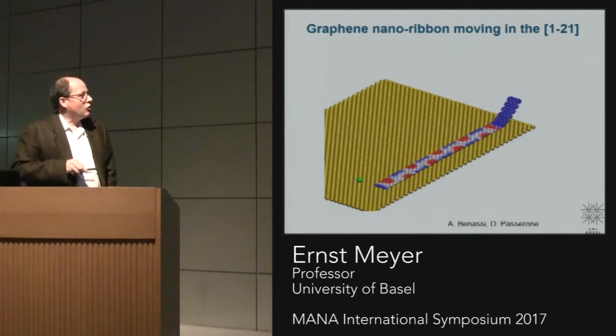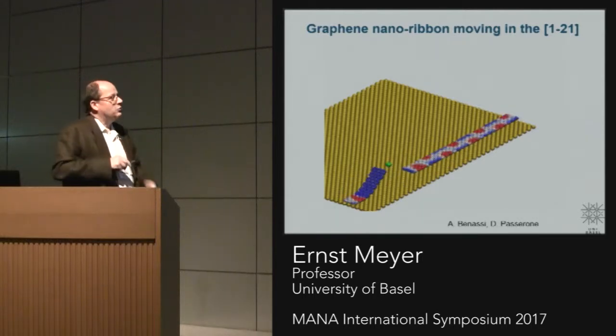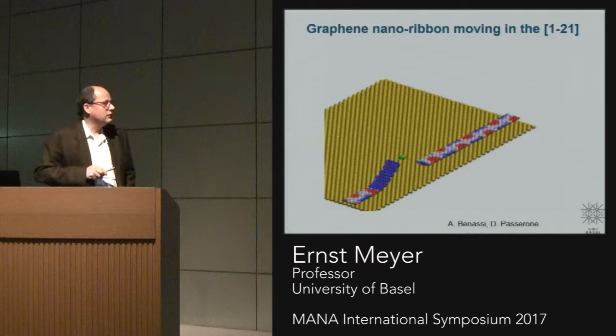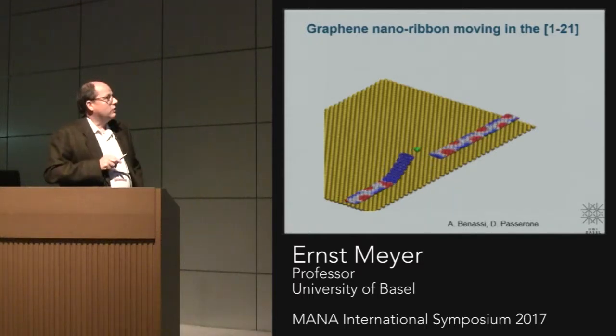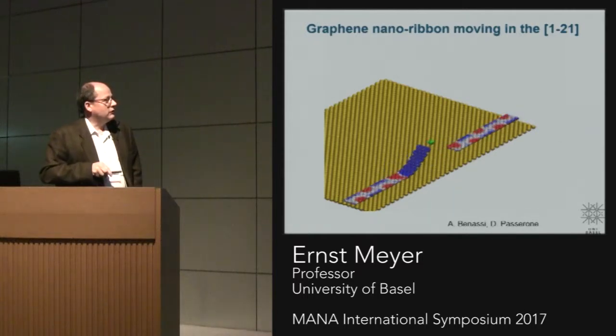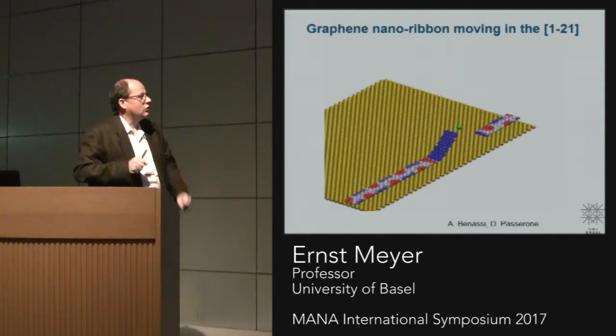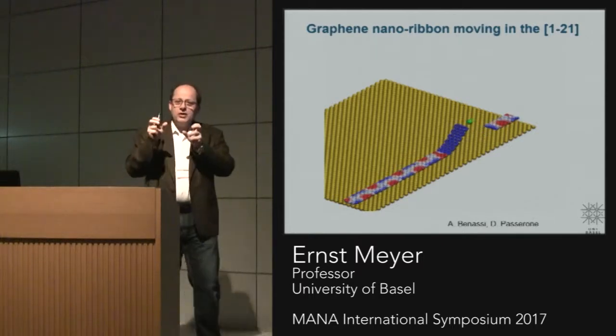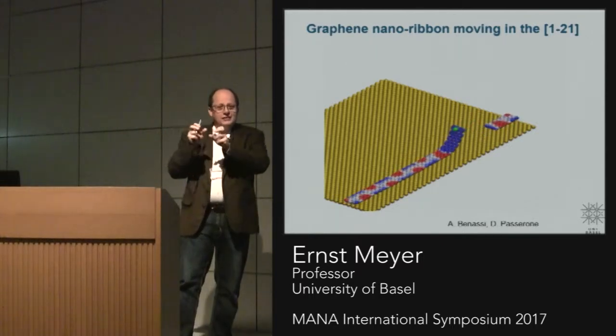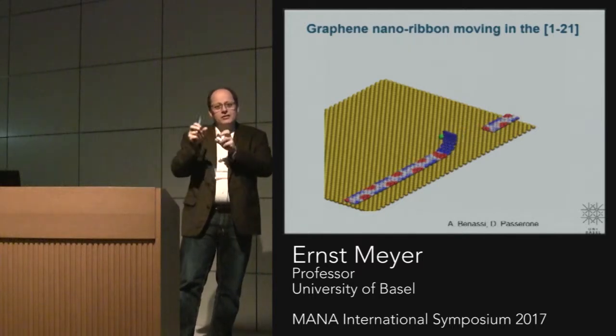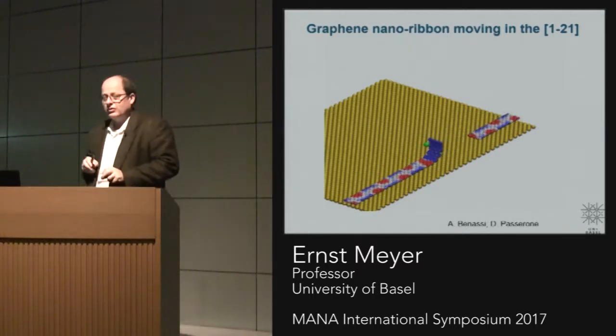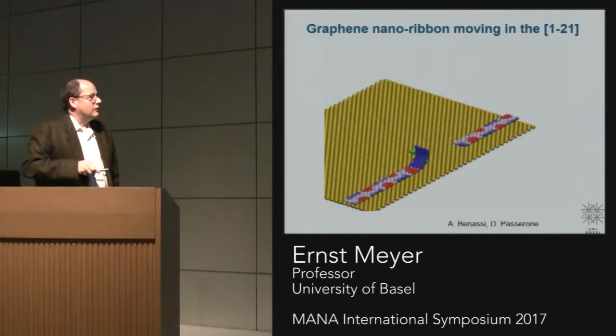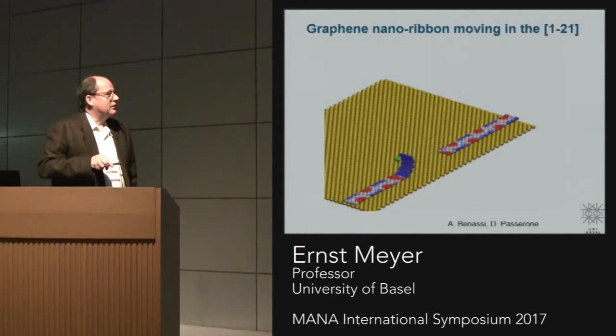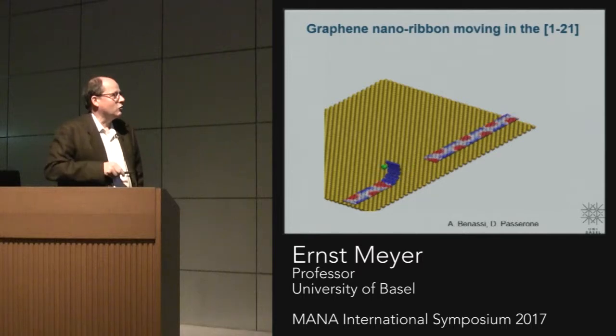And here you see a bit more complicated pattern, a so-called Moiré pattern. So in this case, you see a bit larger frictional forces. It's still practically superlubric conditions, but still there is some remaining force because you have these little Moiré tiles which are not completely compensated. So the Moiré basically just means there are areas where the lattices fit better and areas where they don't, and one resists the motion and the other one not. This is quite a complex pattern.